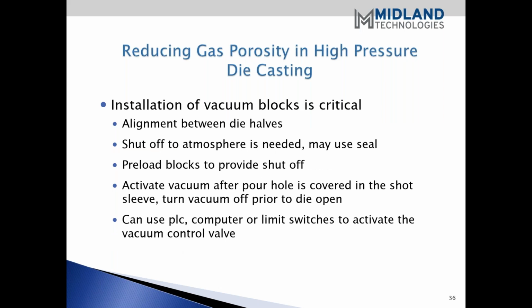Okay, so once we've decided that we're going to go with vacuum, one of the critical areas, or vent blocks for that matter, is to align and ensure ourselves that the two halves of the die are in alignment. And you'll note that if you've dealt with Midland block, there are keys built into the blocks, both vent and vacuum, that align it. It's critical if you were to retrofit that the two halves be aligned properly. In the case of vacuum, of course, you want to shut off the atmosphere. In other words, you don't want to draw air into the cavity.